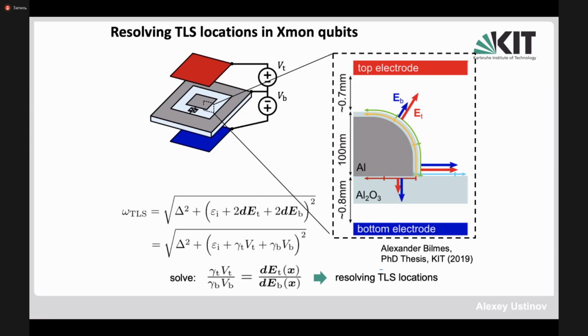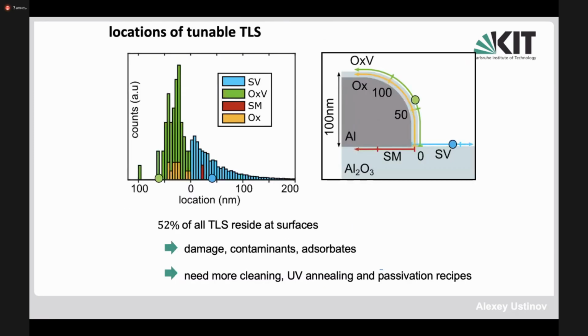sometime later. So this allowed for the first time to really have counts of the number of defects on different surfaces. So you see here that on the interface between metal and substrate, this is this red interface, there are only very few defects detected, whereas when the defects are occurring on the surface of the substrate, these defects are weakly coupled, but they are distributed quite uniformly, and one can count them, of course, with decaying resolution away from the qubit.